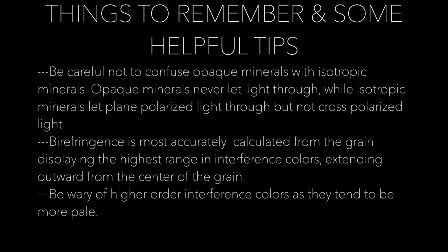Birefringence is most accurately calculated from the grain displaying the highest range in interference colors, extending outward from the center of the grain, and be wary of higher-order interference colors, as they tend to be more pale.